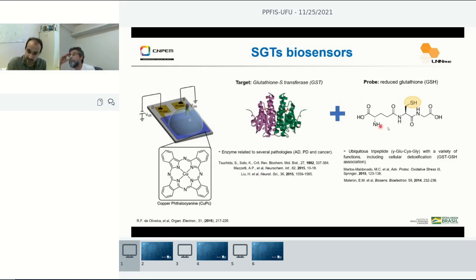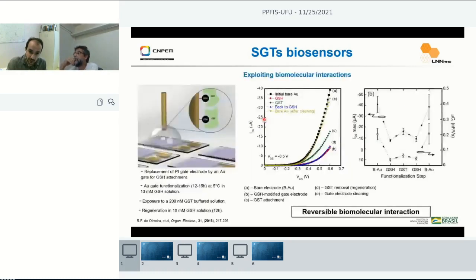So we use this peptide as a bioreceptor to interact with this protein and detect it in solution. So we use a gold wire as the gate, where we use the peptide as receptor that will interact with our protein, GST. So what we did here, we used the transistor to monitor this biochemical interaction, biospecific interaction. So here we have the transistor current as a function of the gate voltage, where the black curve is our initial transfer curve, so where the gate electrode is not functionalized.